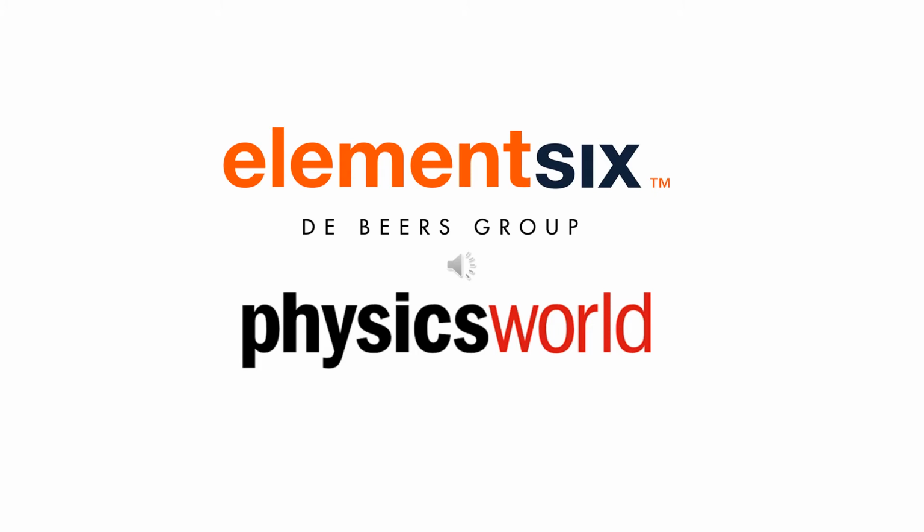And once they're in that ground state, effectively in a quantum system, a quantum bit, your qubit, you can consider that as an up state. By applying an RF field, you can turn it from an up state to a down state. So you can now manipulate that quantum spin once you've polarized them all into one state. Effectively, you have this quantum bit you can initialize, and then manipulate to be in an up state or a down state at room temperature. And that's pretty special and pretty unique.